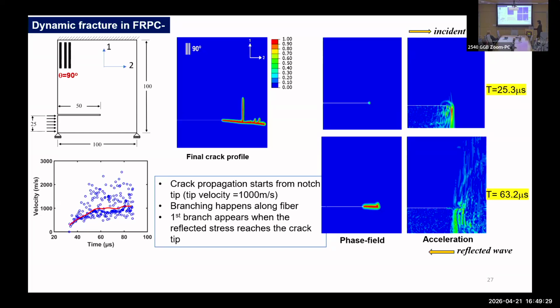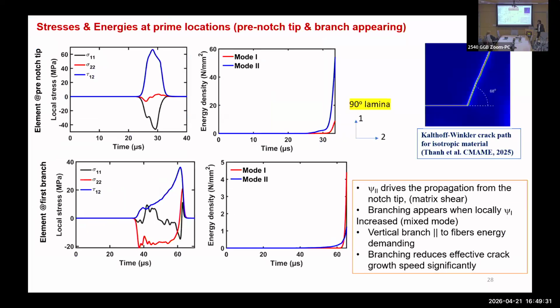But then when it comes back, I will show you the energy spectrum now. Look at the element at the pre-notch tip and the element at the first branch tip. If you look at these two energy plots, you will see it was more mode 2 driven at the beginning. As I said, it was shear driven. But when the reflected wave came back, we saw a mode 1 spike in the energy plot. And that is when we saw this vertical crack start propagating. The first branch appeared.